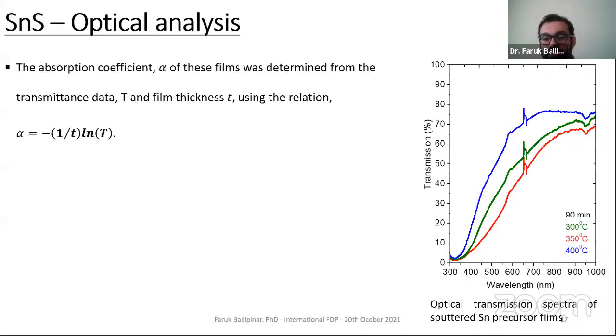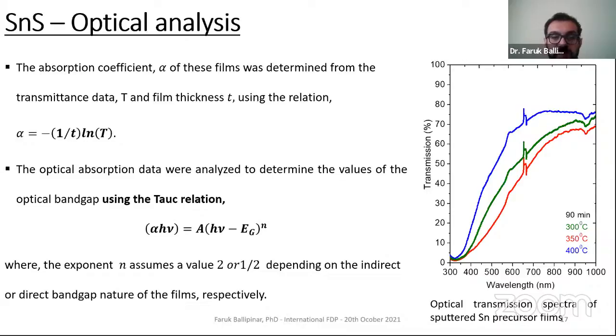Optical analysis is an important step for the application of solar cells. Looking at the 3 samples of the optical transmission, all of them show very sharp absorption thresholds. So these are good candidates for solar cell application. According to Lambert's law, based on the absorption coefficient and thin film thickness, and using the transmission data, using the extrapolation in the specific region of the Tauc relation, we can calculate the direct and indirect band gap of the material.